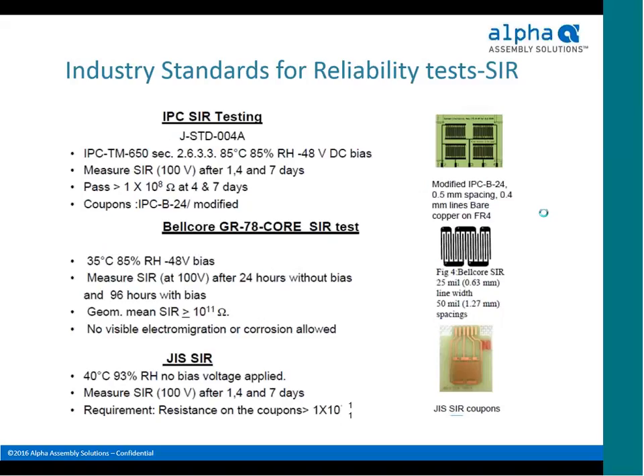Basically, it's 85 degrees C, 85% humidity, and a 48 volt bias across the test coupon, where you measure the resistance across the comb patterns after 24 hours, 96 hours, and 168 hours. In order to pass this test, you have to be greater than 100 megaohms of resistance at the 96 and 168 hour checkpoints, and the coupons are specified by the IPC in their B24 coupon. Basically, a number of comb patterns with a 20 mil spacing across the non-common combs.